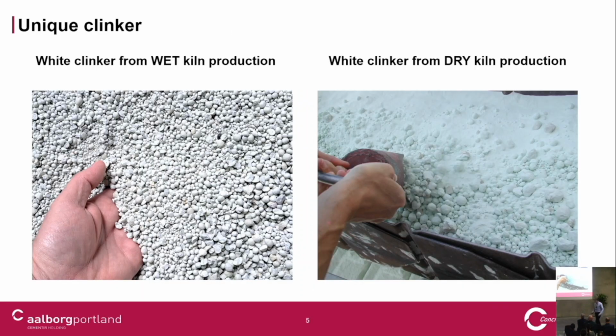So this is to show you an example of how it looks - wet kiln, dry kiln, the clinker coming out here. You should not compare the color, but you can compare the size. You can see here these are small spherical clinker, not the same size, but at least a similar size. Whereas this clinker, from our Egypt plant, which is a dry plant, we see much more dust and also bigger clinker nodules than over here. That's a difference - this is only possible in a wet kiln.